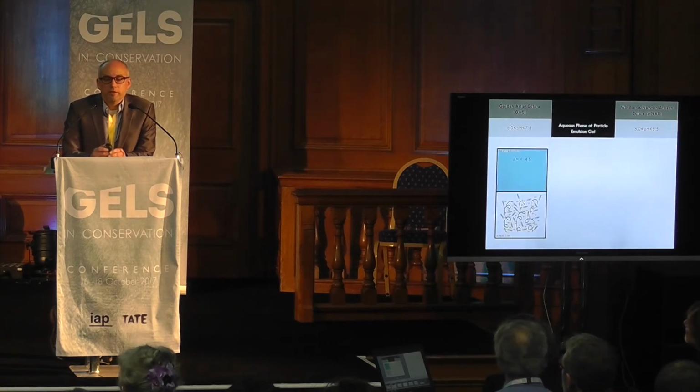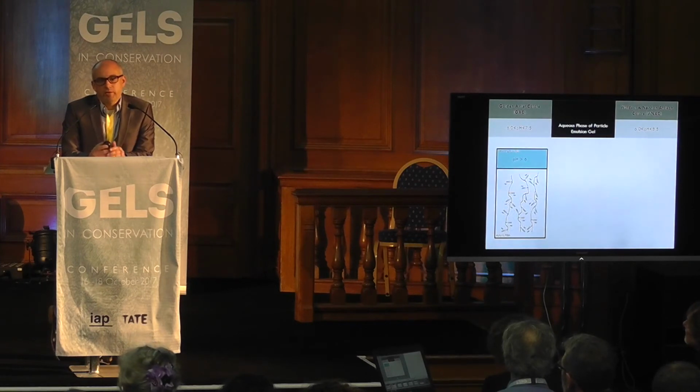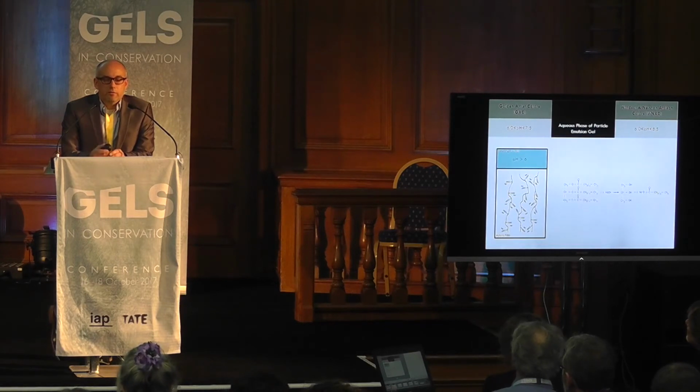In Golden Artist Colors acrylics, we know that the existence of polyacrylic acids is going to swell the paint film, so we don't want to work at too high of a pH and swell that paint film, make it more receptive to water. And so we have to limit our pH, namely by the pKa of that. In the Winsor & Newton Artisan colors, our pH is primarily limited by the saponification of the triglycerides, so typical oil paint film chemistry. And so there's a workable pH range in both these systems.